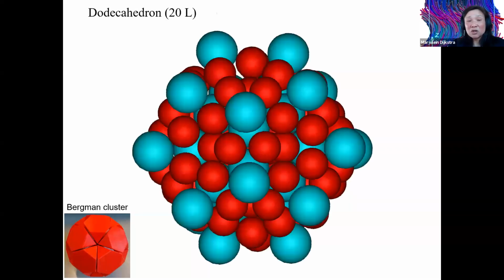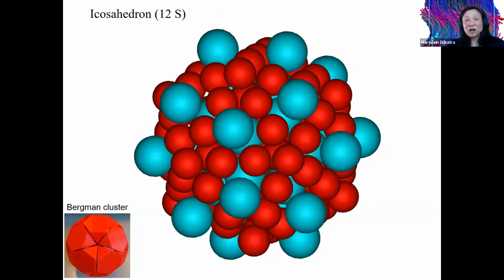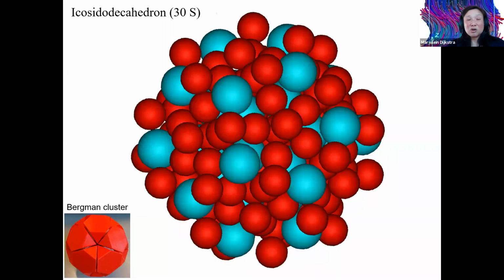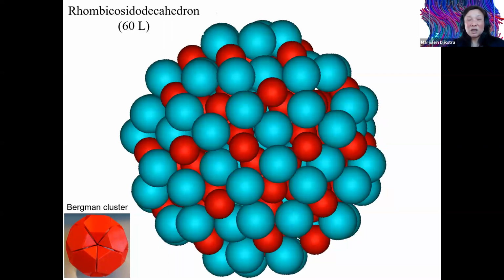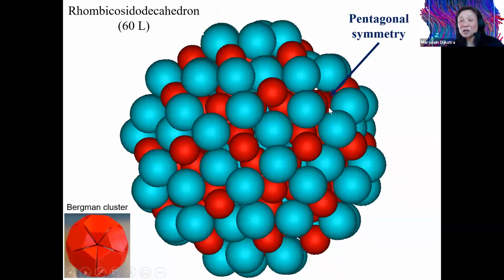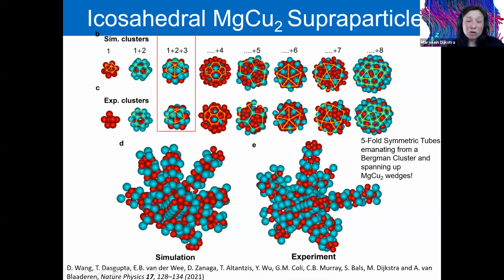But we can now also go further and we found that there's a dodecahedral shell of 20 big spheres around it, then an icosahedral shell of 12 small spheres, an icosidodecahedral shell of 30 small spheres, and then a rhombicosidodecahedral shell of 60 big spheres around it. And one can still see these pentagonal symmetries at the outside of this cluster. One can also zoom into these, let's say, pentagonal tubes. And if you look at that, we find that there are 12 of these pentagonal tubes because it's the icosahedral cluster with 12 of these vertices. They are alternating sequences of big spheres, small spheres, big spheres, small spheres.